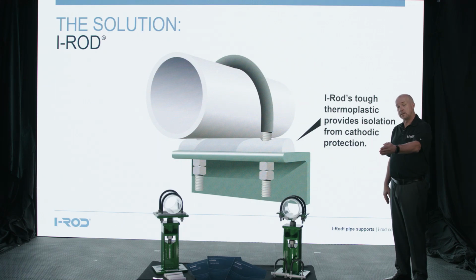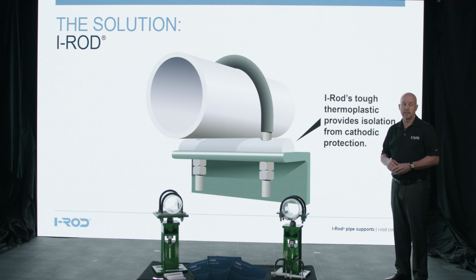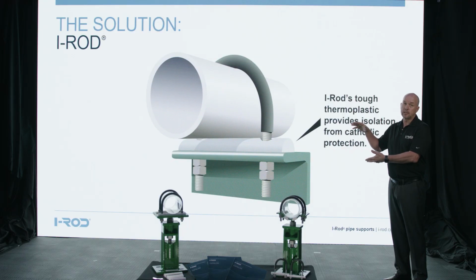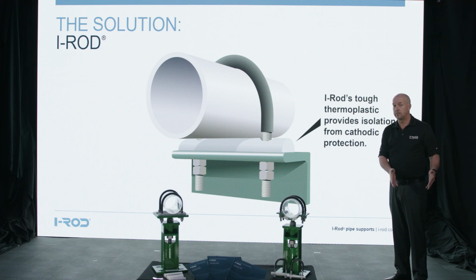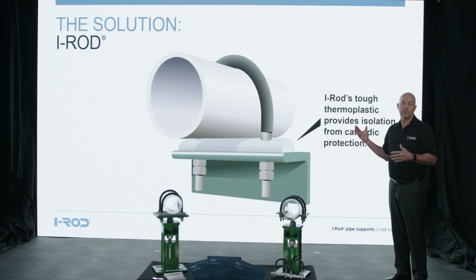And the way that this works is, when the pipe is underground, there's a cathodic protection system in place to protect the pipe underground. Then the pipe comes up out of the ground and it's resting on top of a pipe support similar to these ones here in the front. When that happens, if the pipe is grounded, with the coating removed and the bare steel in contact with the support, and the pipe is grounded to the support, then the cathodic protection system can be drawn to that base of the support, which then causes the cathodic protection system at the end of the system to fail prematurely, which can be very costly. However, if you install IROD and isolate the pipe from the support, you eliminate the possibility of this happening.